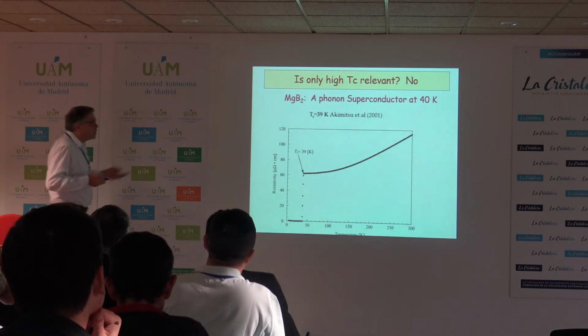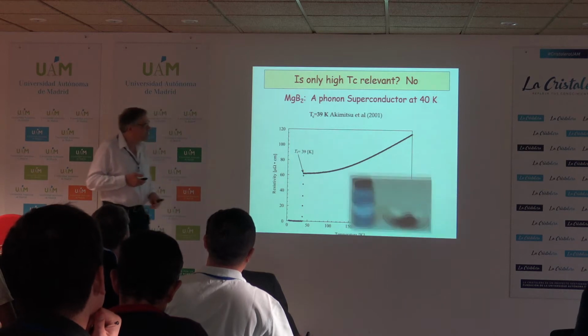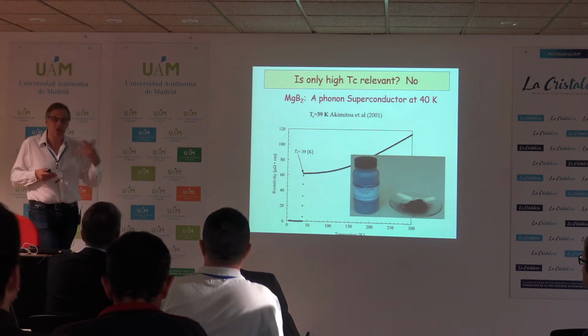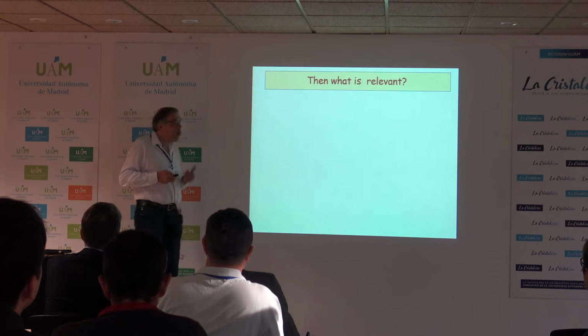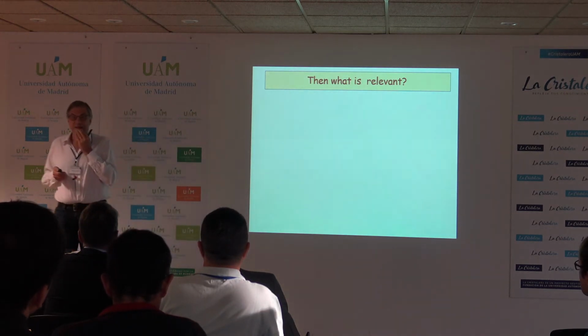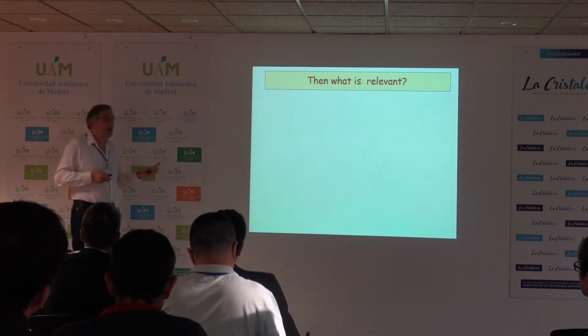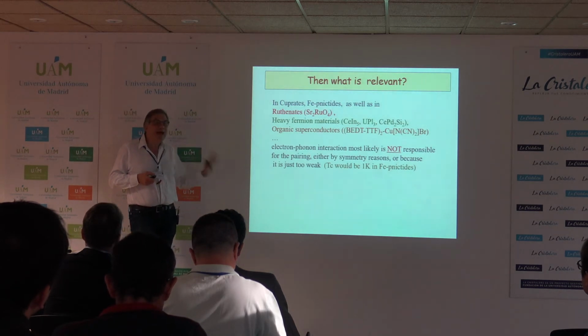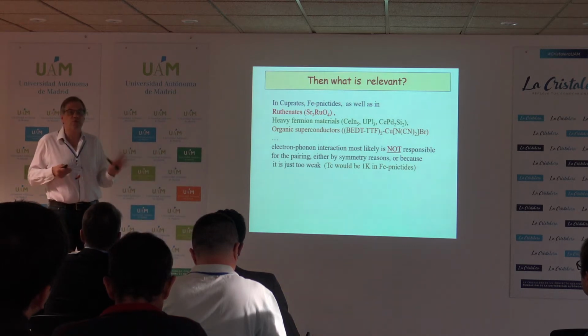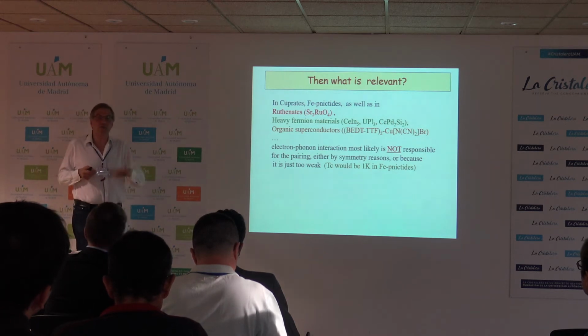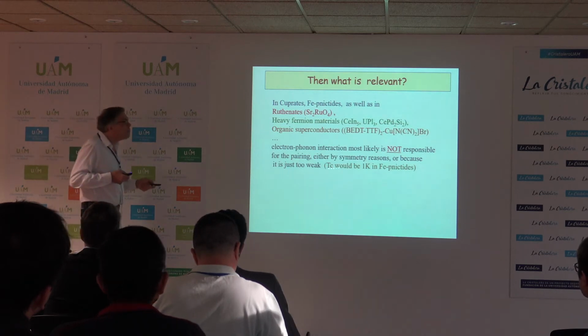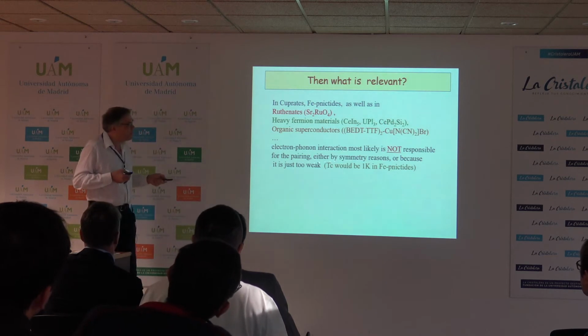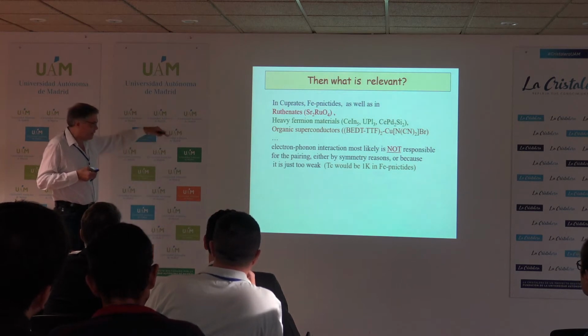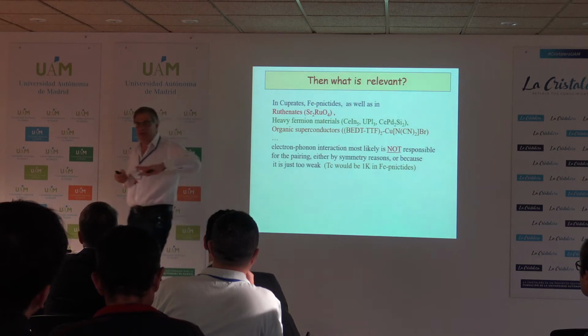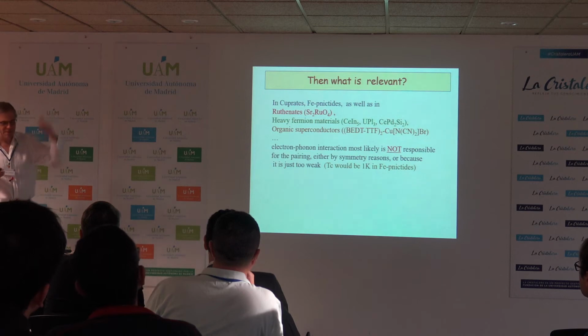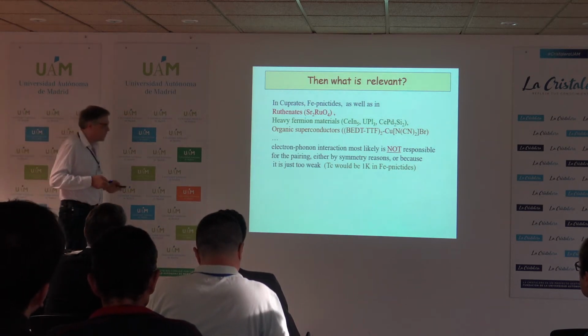Well, partly the answer is no. This is one example, and MgB2 is definitely a phonon superconductor with Tc of 40 Kelvin. The record highest superconducting temperature under pressure is also for phonon-mediated superconductors. So why are we talking about electronic scenarios? And at this stage, the answer will depend on whom you ask. My point is that in a number of materials, it is not entirely guaranteed, but there are good arguments that for one reason or another, electron-phonon interaction will not work. Either by pairing symmetry, electron-phonon interaction just will not give you the pairing symmetry that is observed in the experiments, or by purely numerical reasons. This is one example that I like to cite: people who promote electron-phonon interaction calculated Tc for iron pnictides and found that even without the negative effect of electron-electron interaction, you get roughly 20 Kelvin. You can make it larger by 5 Kelvin, but not 60 Kelvin. That is the highest temperature seen in experiments.